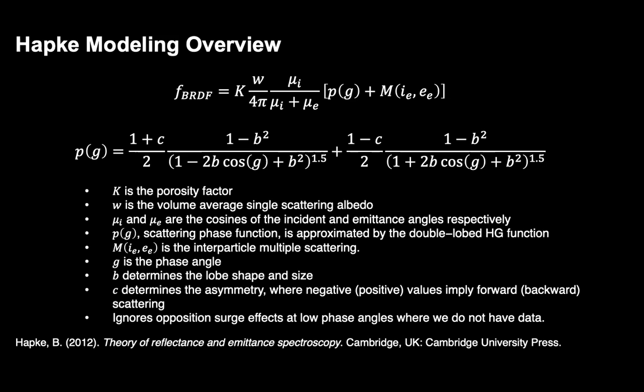There's a lot of these, again, various space weathering processes and meteoritic bombardments that allow the soil to kind of be very thinly distributed. You get these fairy castle structures and things like that in the soil. So at the lunar surface, you're really looking at about a 0.8 porosity factor there. In the laboratory, though, that's going to be different. These soils that we're looking at in the laboratory, the Apollo soils as well, let alone the JSC1A, they've been on Earth for some time, and they're going to compress down. So for our modeling here, we've assumed an intermediate porosity, a 0.5 porosity there. The W there is the actual single scattering albedo, the mu I and mu E, those are the cosines of the incident and emittance angles respectively. And then that P is a function of G.